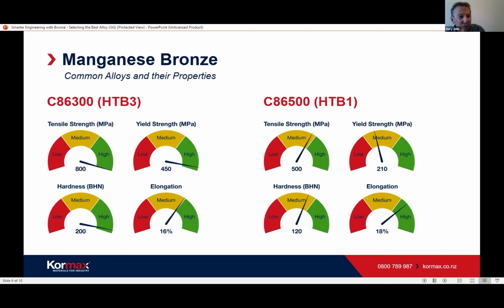And the final one is the manganese bronzes. They're also known as high tensile brasses. They're actually a brass, but they're called a bronze, so that's just one of the peculiarities of the naming system of copper alloys. The common one in that is C86300 or HTB3. You can see from those graphs, very, very high strength. Higher strength than mild steel or reasonable steels at 800 megapascals. Very good yield strength, high hardness, and still good elongation at 16%.